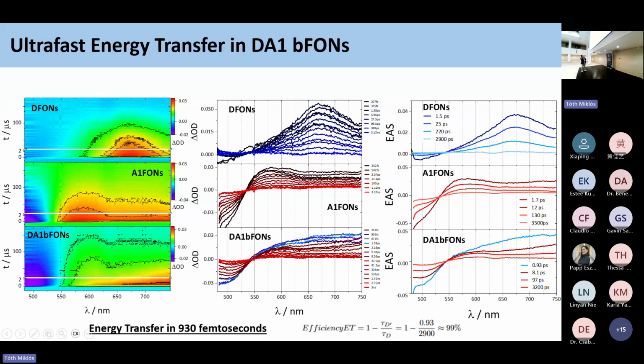Coming to the binary nanoparticle, we see an interesting behavior. In fact, both the matrix and the spectra seem to be dominated by signal only associated with the acceptor. So to give an interpretation, we took a look at the evolution associated spectra, from which the only transient that seems to bear features relative to the donor is the first one, which has been fitted with a lifetime of about 900 femtoseconds. So indeed, the energy transfer seems to be very fast and seems to happen in the sub-picosecond time domain. And we tried to give an efficiency for the process by taking into consideration a Stern-Volmer model, taking into account the lifetime of the donor in the single component nanoparticle and the lifetime of the quenched donor in the alloy nanoparticle, and we have obtained an efficiency for the process over 99%.